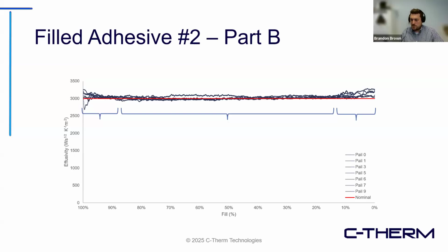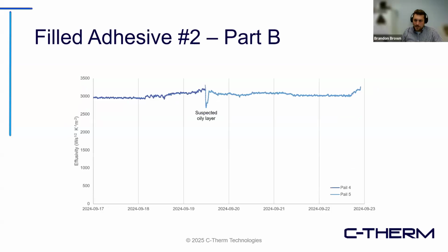In the middle, we have a zone of stability spanning about 80% of the pail, and finally at the end of the pail, where the filler would have settled to, you can see a slight increase in effusivity. All of these pails perform quite well, but right at the start of one of the pails, which I believe is pail 5, you can see there's an off nominal dip in effusivity. So let's investigate on the next slide.